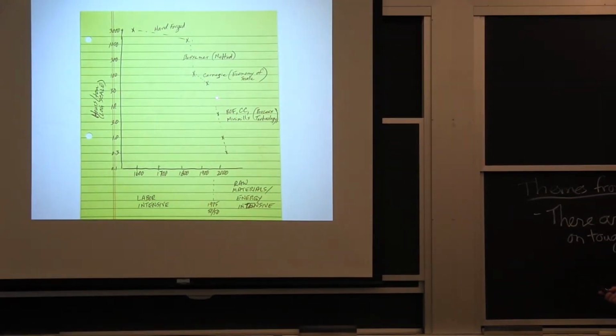And then we came up in the 60s with the basic oxygen furnace, continuous casting, mini mills, which were smaller, a way to use a lot of scrap. And here we went from labor intensive in 1975, when I worked for Bethlehem Steel, it was 50-50 labor materials. Actually, it was 45-45, and they actually made a 10% profit. In the 1980s, it was 55-55, and they made a 10% loss. That's another story. Raw materials, energy intensive today, okay? That's what it takes to make steel. Doesn't take much labor. We're down to 20 minutes a ton, okay, per person ton, or whatever.